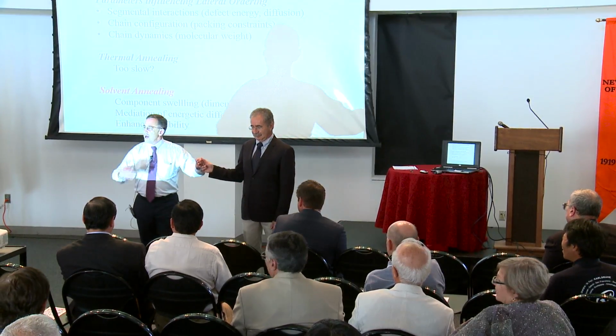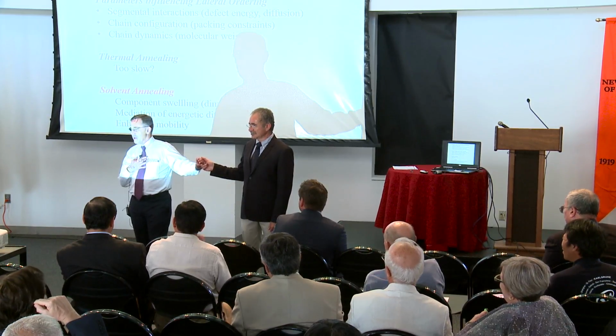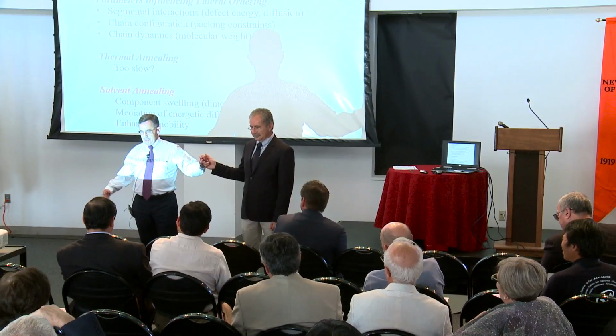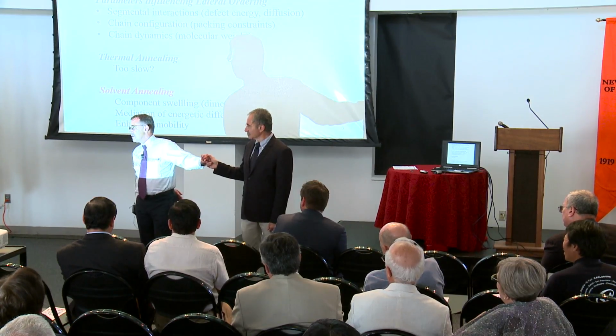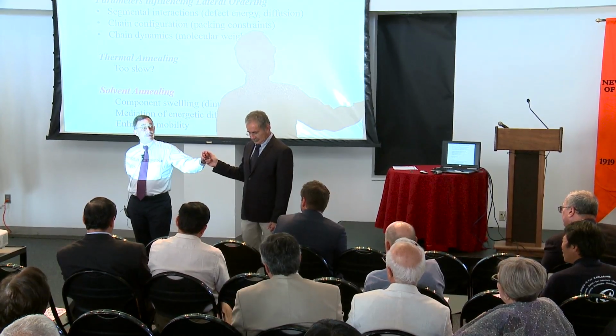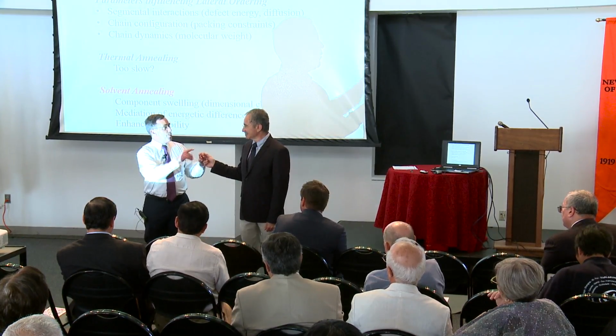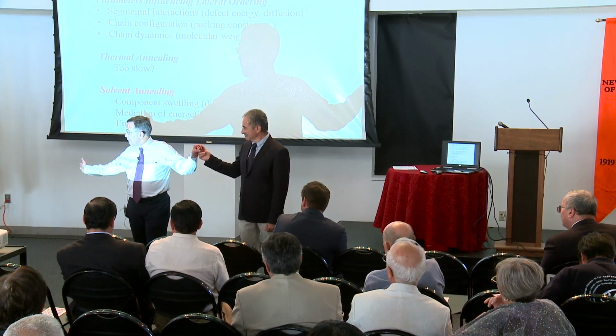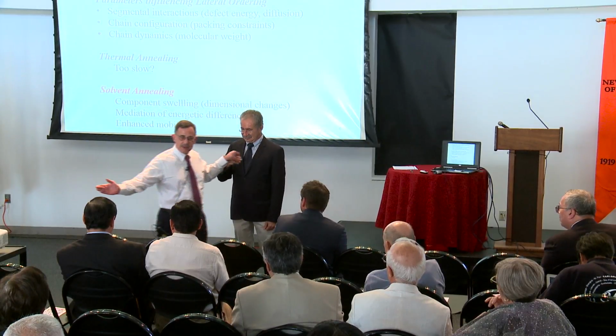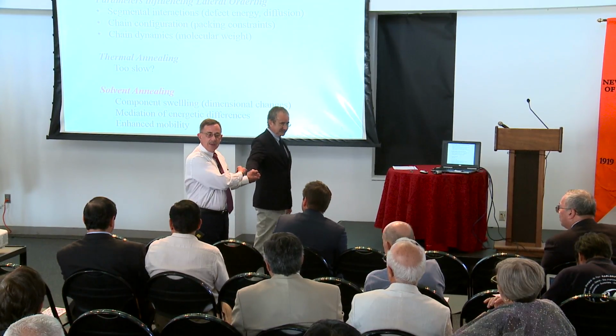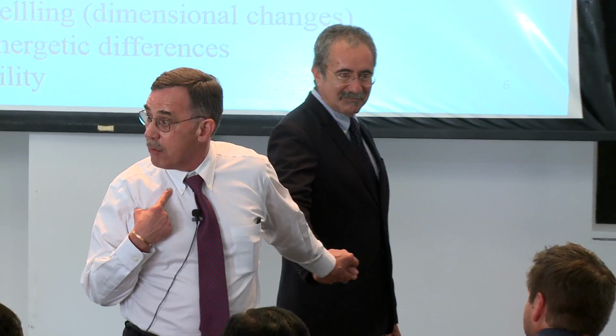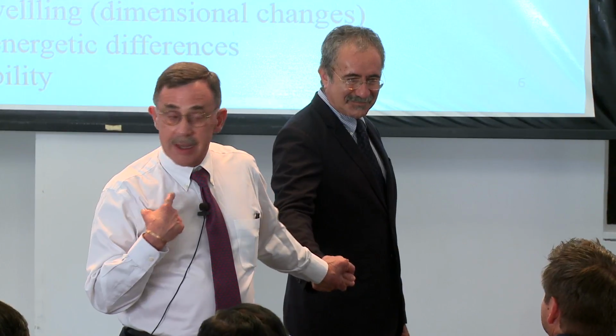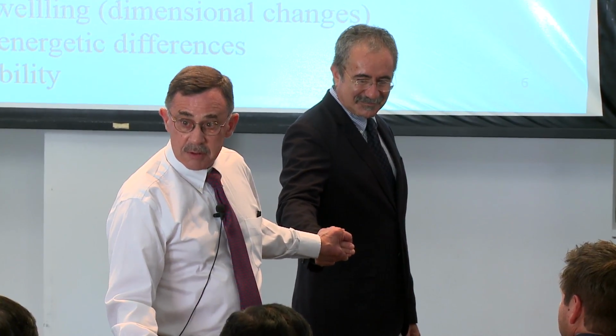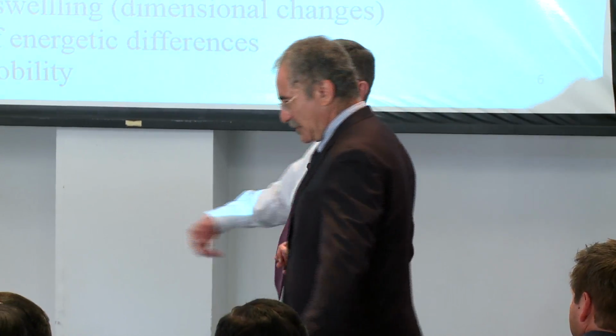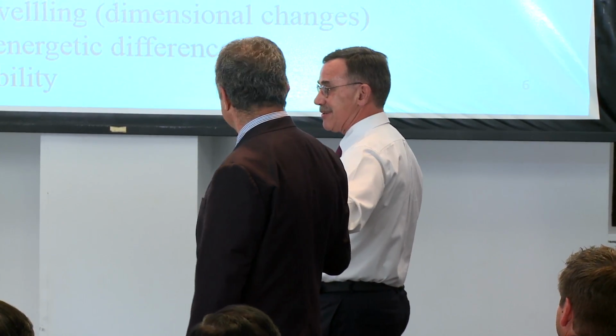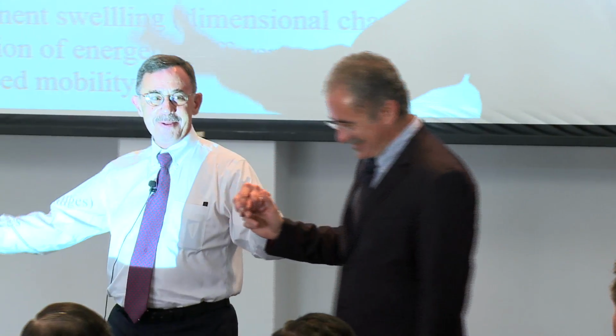So, I happen to be a polymethylmethacrylate domain, and he happens to be polystyrene. The first row of chairs here is the silicon substrate, which grows an oxide. I am polar, you aren't. And so that means if I were to take a film and spin coat it, I go automatically to the surface. We're connected, so where he goes is dictated by where I go, just because of the connection. And if this happened to be an apolar surface, then we'd do the other way. And if it happened to be a surface where the interactions were balanced, then we both go down.